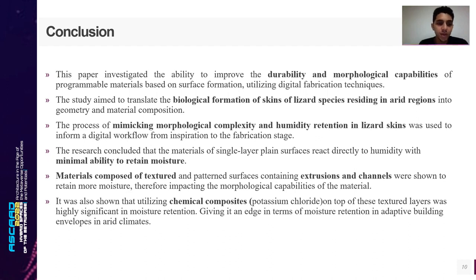In the experimental part, the research concluded that the material of single plane layer reacts directly to humidity with minimal ability to retain moisture, while material composed of textures, extrusions, channels, and patterns was shown to retain more moisture than the other. It was also shown that utilizing chemical composites like potassium chloride on top of these textured layers was highly significant in moisture retention, giving it an edge in adaptive building envelopes in arid climates.